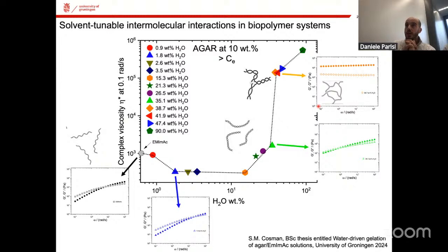So here we now have agar. Let me remind you that agar is partially soluble in water, and in fact, it can even make gels in water. So let's say it's more hydrophilic than cellulose. And here we are reporting the viscosity as a function of water content. It means that when the content of water tends to 0, so these are log-log plots, so there is no 0 here, it is basically the pure ionic liquid used as a solvent.